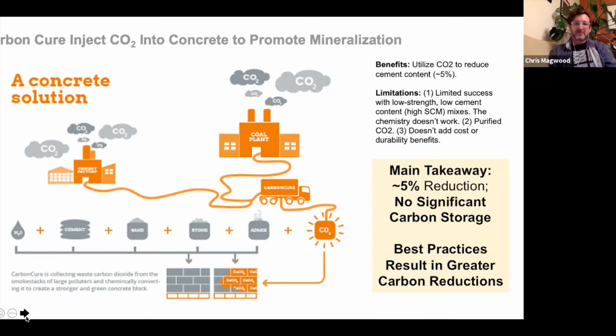There are some limitations to this approach. So number one, there is limited success with low strength, low cement content mixes. So if you have a really high SCM mix, the chemistry just doesn't necessarily work as well. And then the utilization of purified CO2 and the fact that the CO2 doesn't really add cost or any durability benefits are really limitations. So the main takeaway for CarbonCure is that it is great. I think it's a good technology, but really it's only somewhere between 5 to 10% reduction that is achievable. And so there's really no significant carbon storage. And I really would recommend to clients that the best practices that I discussed earlier result in much greater carbon reductions if you're looking for that. Next slide, Chris.